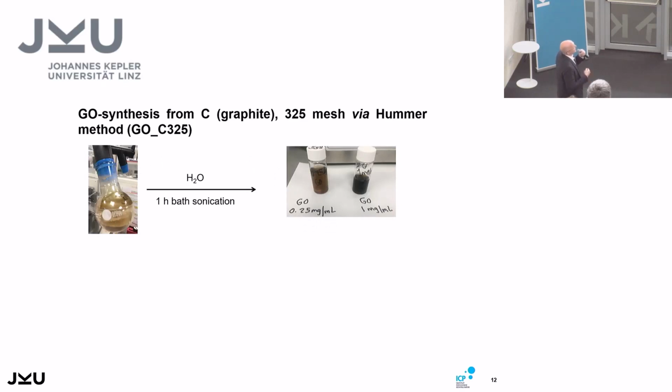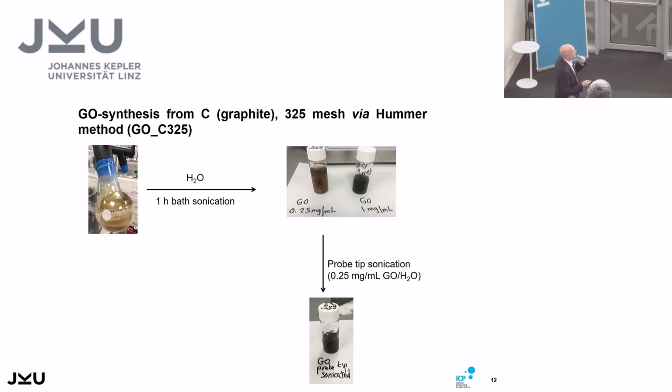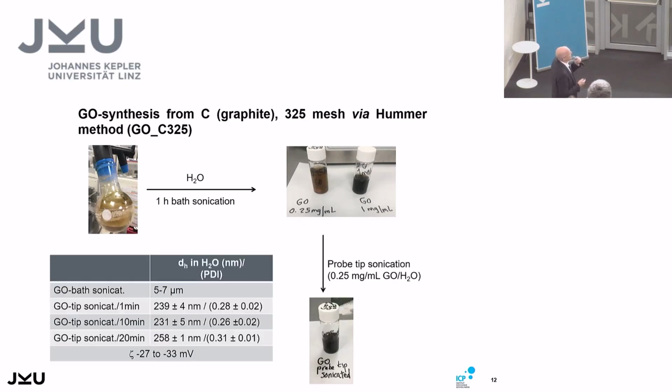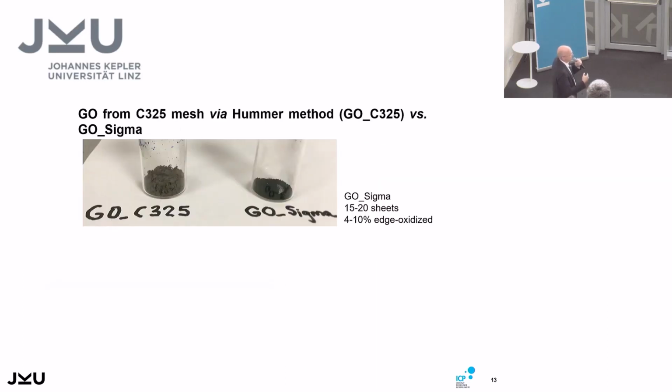And of course, we wanted to, first of all, create a dispersion. We sonicated that, and only after tip sonication, we found out that we got nanoparticles. Before, with only simple sonication, it led to aggregates, micrometer-sized, 200 nanometer-sized; much tinier fragments or particles we obtained after this tip sonication.